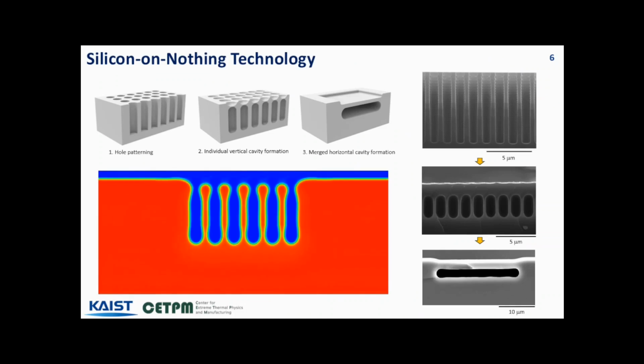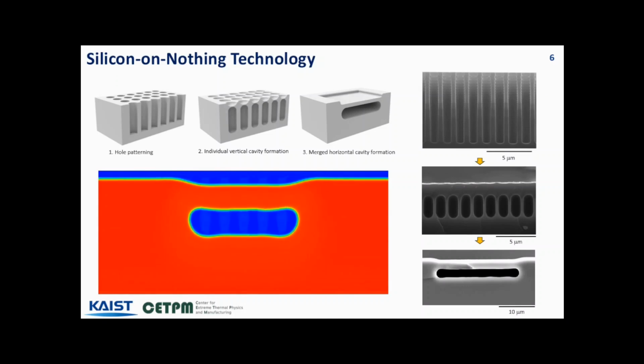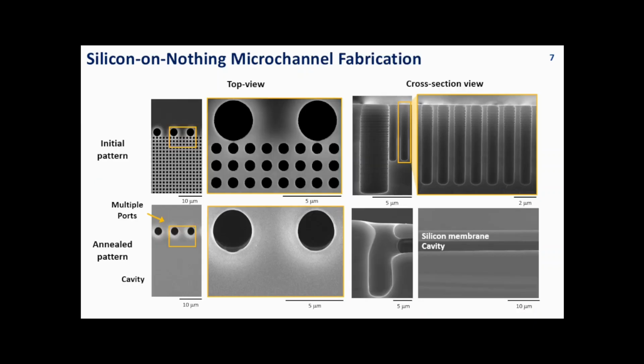We fabricate the microchannels using silicon-on-nothing technology. Silicon-on-nothing refers to a monocrystalline silicon thin film suspended over an empty space, which is formed through surface diffusion when a silicon hole array is annealed at high temperatures. As shown in the image, initially individual vertical cavities are formed, and as the annealing progresses, these cavities merge to form horizontal cavities.